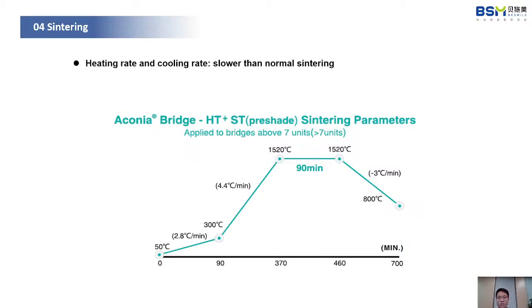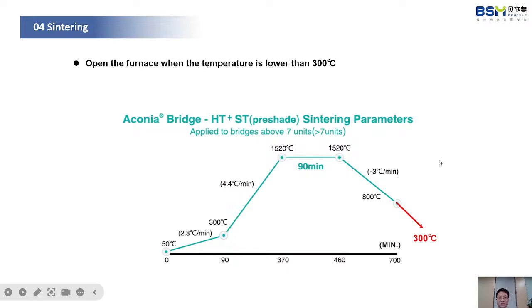Especially for long bridges, we need to make sure the heating rate and cooling rate are slower than normal sintering. This is the recommended sintering curve for zirconia long bridges above 7 units. After sintering, we need to make sure that when we open the furnace, the temperature is lower than 300. If we open the furnace at a very high temperature, maybe 500, the cold air will get into the furnace, and when the restoration